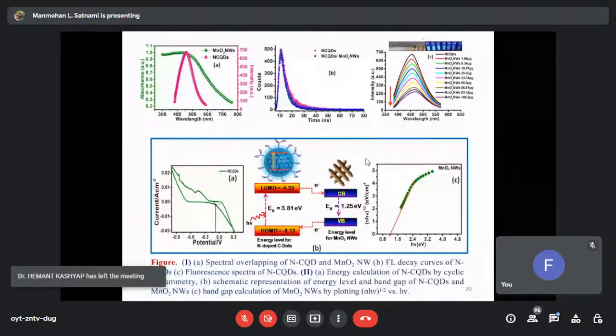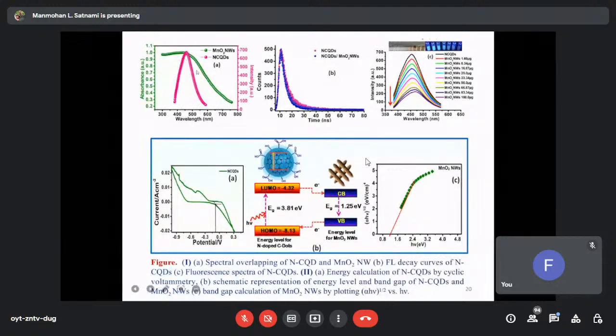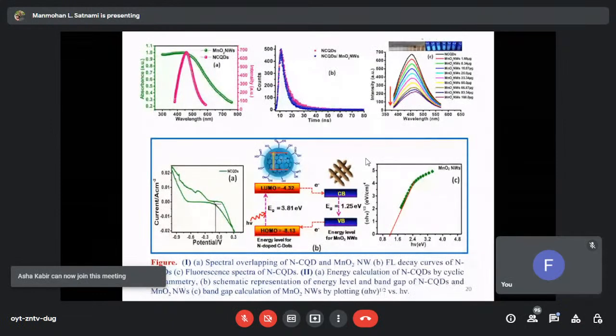If you can see, this green line shows the absorption spectra of MnO2 nanowire, and this pinkish line, this graph, shows the emission spectra of carbon quantum dot. So you can see this is the complete space which is overlapped between the absorption spectra of MnO2 and the emission fluorescence spectra of carbon quantum dot. Therefore, we enlarge the size of this figure. You can see the rods very clearly.